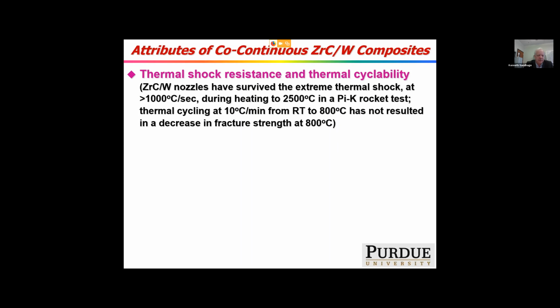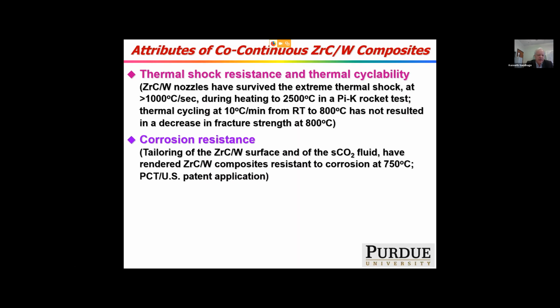I've already shown you that with a Pi-K rocket test. But even with more modest heating, 10 degrees a minute from room temperature to 800 C, and then measuring mechanical properties afterwards, we've not seen a degradation in fracture strength after such cycling. I don't have time to get into it today, unfortunately. I'm happy to talk to you about it if you're interested. But we've also learned how to tailor the surface of ZrC-tungsten and of the supercritical CO2 working fluid so that they're resistant to corrosion, even after 1,000 hours at 750 C at 20 MPa in the supercritical CO2-based fluid.